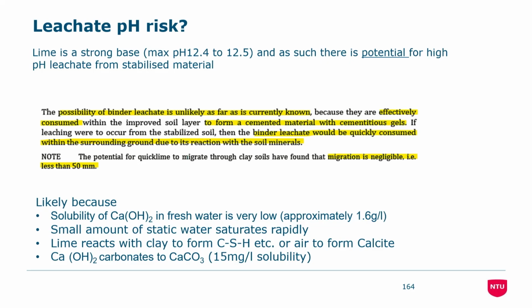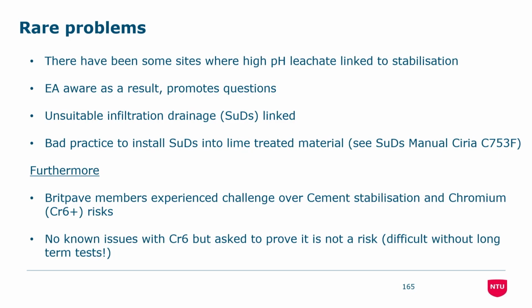Also, in a reaction that we're promoting here, where lime is reacting with clay, we tend to form cementitious bonds like calcium silicate hydrates, and also that's what the cement itself would go on to produce. And when that reacts with carbon dioxide or carbonate from air in water, we're likely to form calcite. Calcite itself is incredibly low solubility compared to the lime, about 15 milligrams per litre. And so it's probably a relatively self-sustaining problem. So you go, well, why are you looking into it then if it's not really a problem?